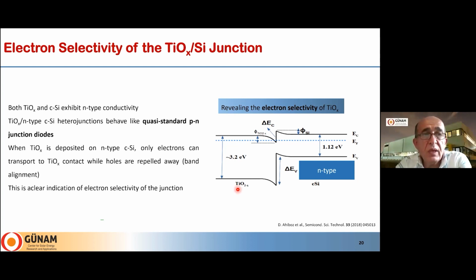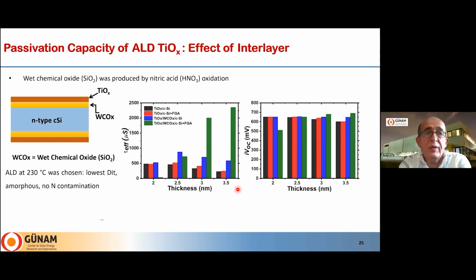Later on, we looked at the passivation quality of ALD grown titanium oxide with chemically grown oxide and without chemically grown oxide. This is the symmetrical structure we use routinely for testing the lifetime of silicon. On the right side, you see the lifetime and the implied VOC values as a function of thickness of the titanium oxide layer.